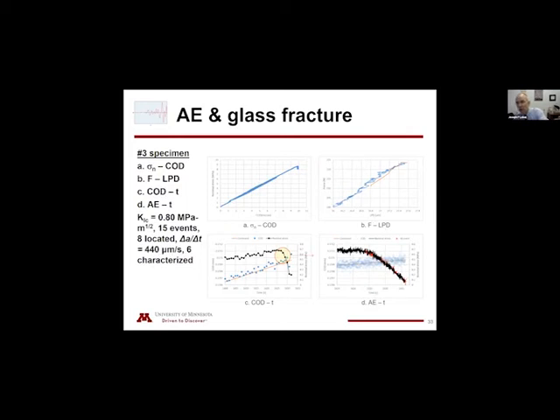This is a portion of the force load point displacement. The blue is loading, peak load takes place, and you see the severe snapback as we are controlling with increasing COD. This is the command signal, so I'm showing you the COD with time. It should be increasing linearly. The blue dots are the actual measurements. So the difference between the feedback signal and that blue dot is the DC error, and the system wants to minimize that DC error. And you'll see at the end, when it was not controlled, the DC error is increasing. This is a blow up around peak load, and the red X's are associated with where we recorded the events.